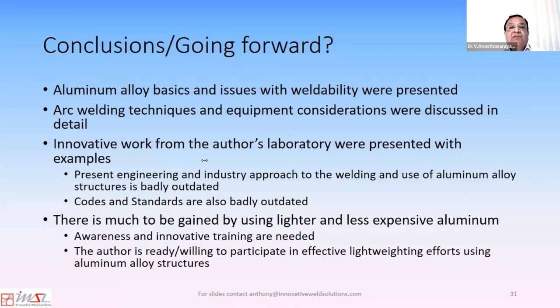Preheating and interpass heating required for aluminum welding? If yes, and when and why? Actually, I recommend against preheating and interpass heating. Mainly because when you do these, there is a higher tendency to oxidize the joint. And if you're doing short length, multiple welds, like in a door panel for an automotive assembly, oxidized areas are not very good. So I would recommend against preheating and interpass heating